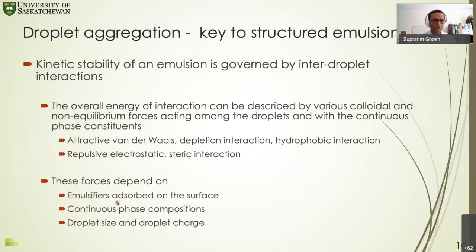And these forces depend on what emulsifier is adsorbed on the surface of the droplet, and the continuous phase composition, and also droplet size and droplet charge. But these are all interrelated. What kind of emulsifier is adsorbed on the droplet surface will dictate droplet charge, and what kind of composition the continuous phase has dictates also droplet attraction and droplet size. So they are all interrelated factors.